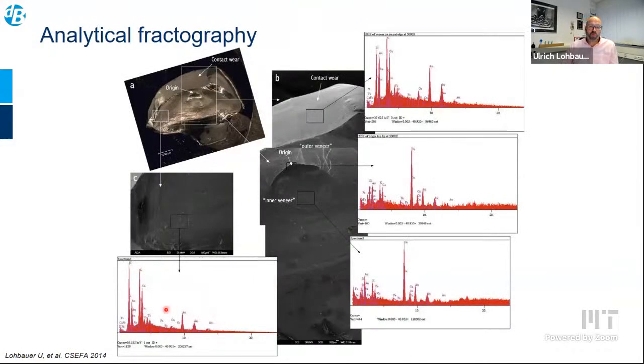We can further, once we retrieve such a piece from a broken crown, investigate the fracture origin. We can add analytical features, and we can say, okay, there is something in the material that should not be. There are heterogeneities, so the reason for failure is easily located. Then you can see where this material is coming from in the process, and then you might recommend any improvements in the dental technician's process.